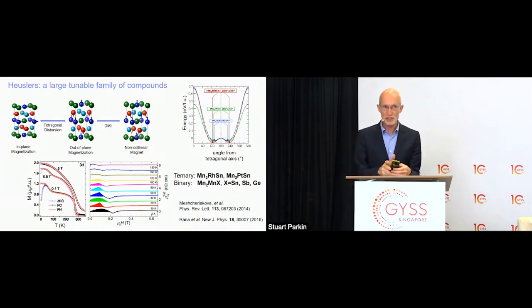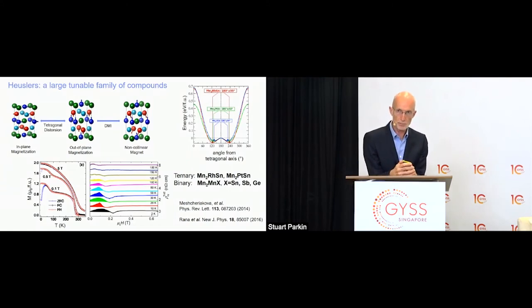So I want to briefly discuss these magnetic skyrmions. And here I want to just turn to a very interesting family of compounds called Heusler compounds. Heusler compounds are a set of materials discovered several decades ago and were of interest because they involve no magnetic element, iron, cobalt, or nickel, but rather manganese, and these materials were found to be ferromagnetic. They consist of four interpenetrating FCC, face-centered cubic, lattices. When the systems are magnetic, the lattice is distorted, becomes tetragonal, and this means that the magnetization will automatically be aligned along a particular direction, the tetragonal direction.